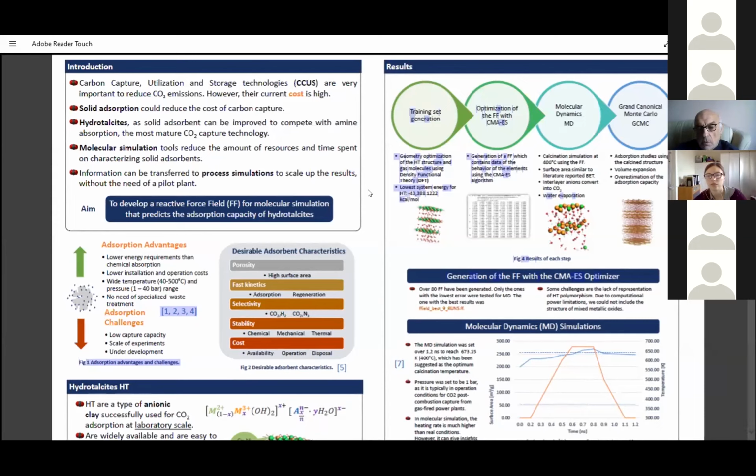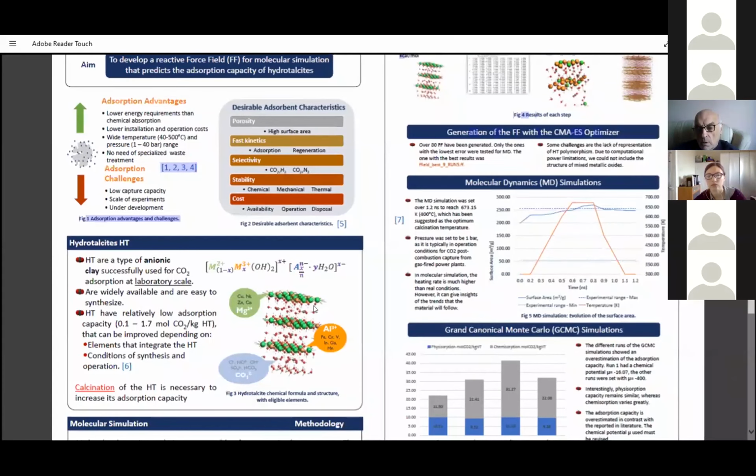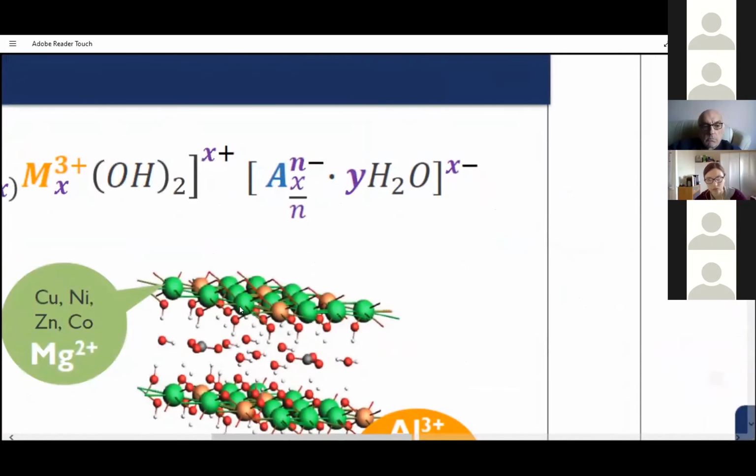Also, when you calcine it, the anions, which are water and carbonates, are removed: the water evaporates and the carbonates decompose into CO2, ironically. But it can capture more CO2 than the amount you generate when you calcine it. If this structure was preserved, it would be around these changes, with green being the magnesium and orange being aluminum. Everything is crumbled up, but this would be the active site.